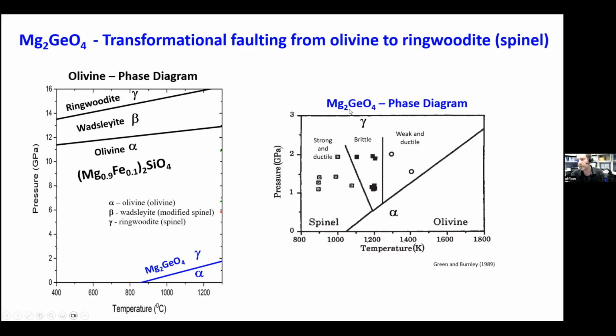They took some Mg2GeO4 and then they deformed it and heated it up. And what they found is if it remained metastable and they didn't generate the transformation, the mineral would be ductile. If they heated it up a lot and they generated a lot of transformation, it would be ductile. But there was a sort of temperature sweet spot in the middle where if they just generated a little bit of spinel, it would be enough to cause the mineral to break.